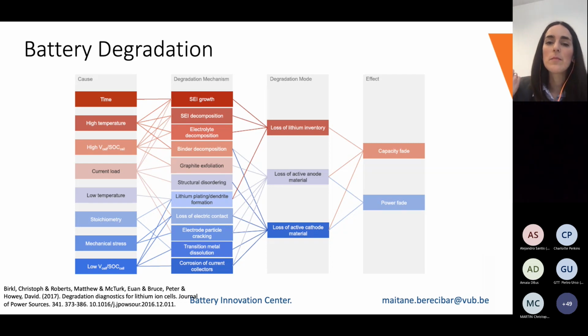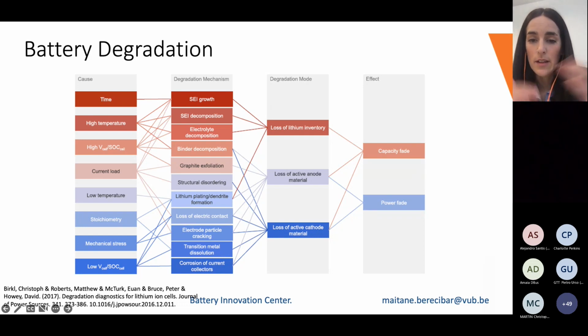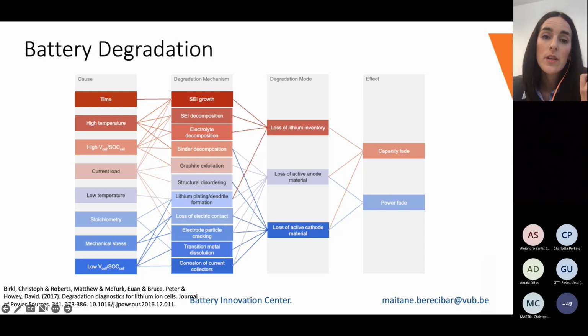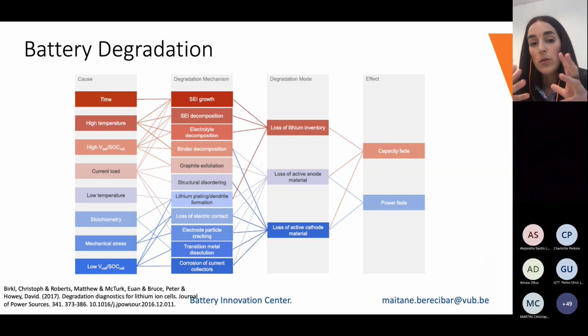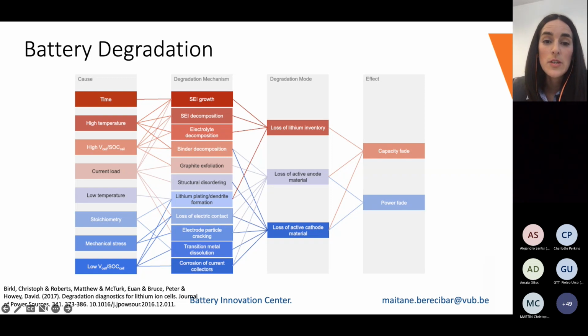Why is this happening? Which are the background degradation modes that we have? Well, there are different ones, depending on if loss of lithium in the battery is happening, depending on if loss of active anode material is happening, or depending on if loss of active cathode material is happening. You can see here that there are different colors, and if we go one step back, this is linked, and that's why the colors, to the different degradation mechanisms. This is a little bit of a summary, and what we can see is that, for example, binder decomposition can happen, graphite exfoliation can happen, structural disordering can happen, electrode particle cracking can happen, and this will lead to the different degradation modes.